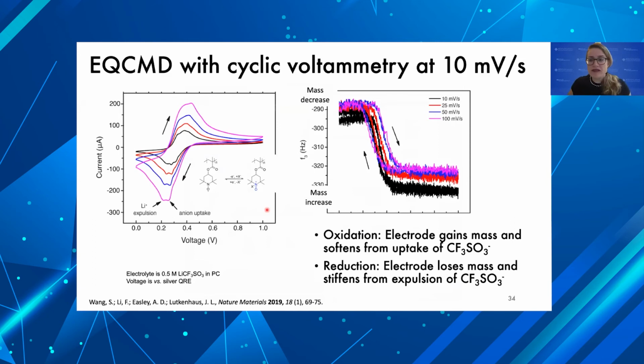Here's the same data, but instead of plotting it in the time domain, we plot it in the voltage domain to give you the conventional sense of a cyclic voltammogram. What we see here are these little bumps in the cyclic voltammogram that we can now assign, thanks to QCMD, their physical meaning. We were thinking that most of the ion transport occurs by anion transport from the doping, but what we discovered in this exercise was that there's actually some lithium cation transport occurring as well, and that's assigned to the lower potential peaks and shoulders.